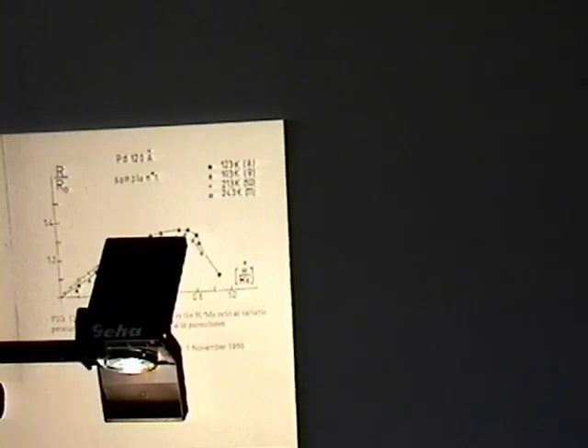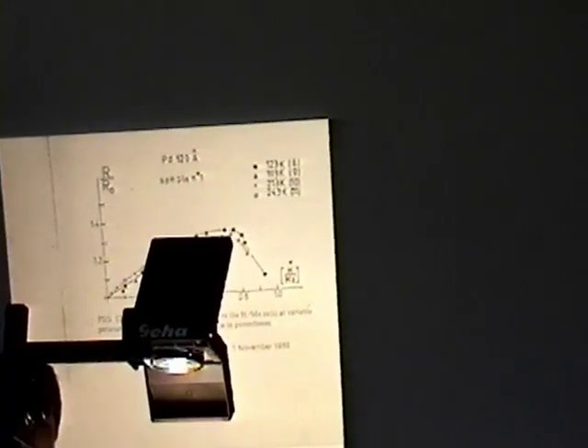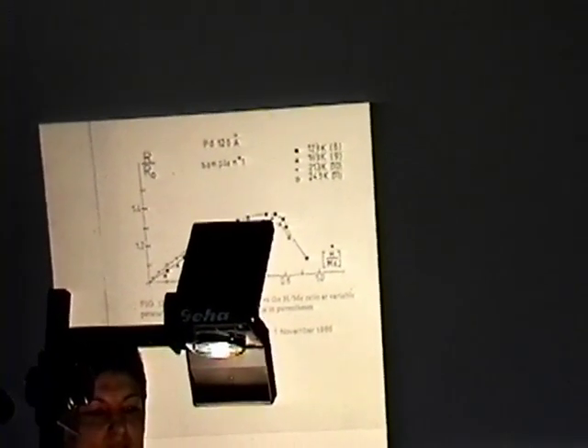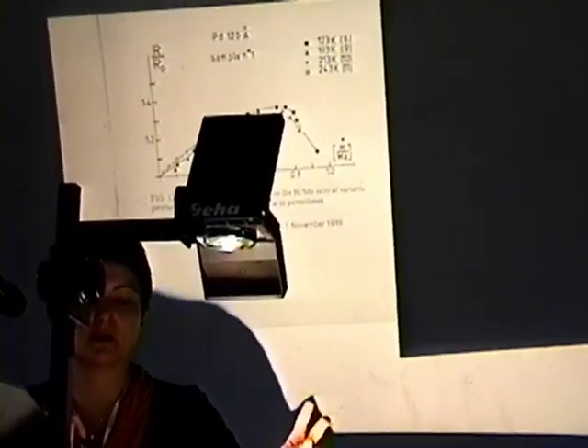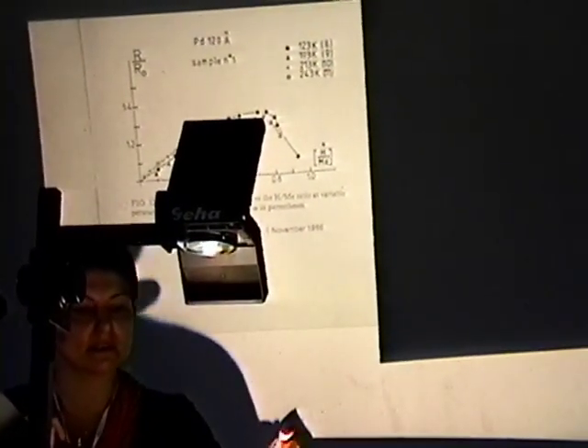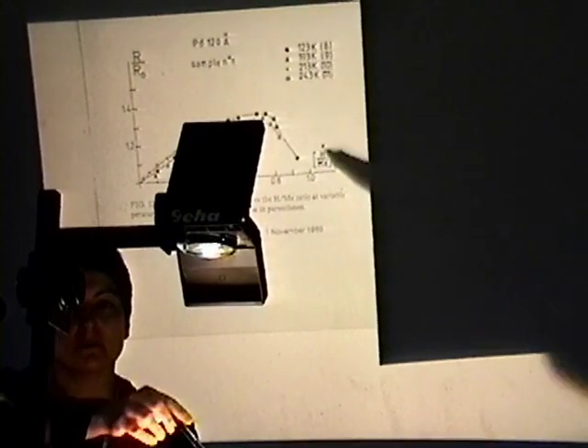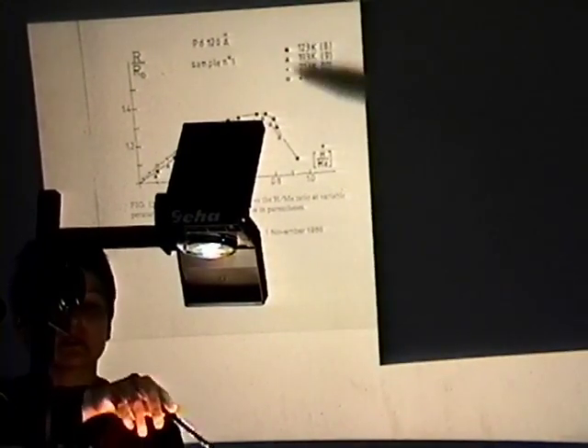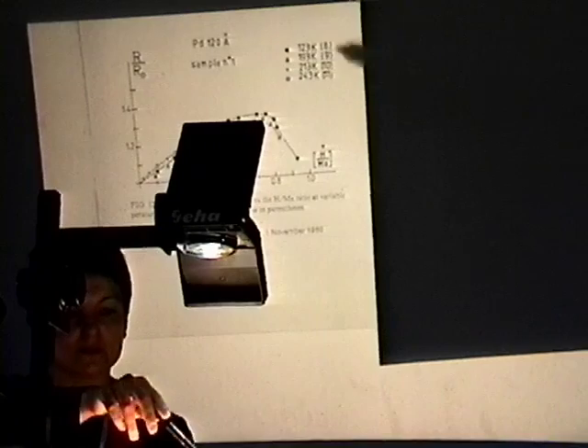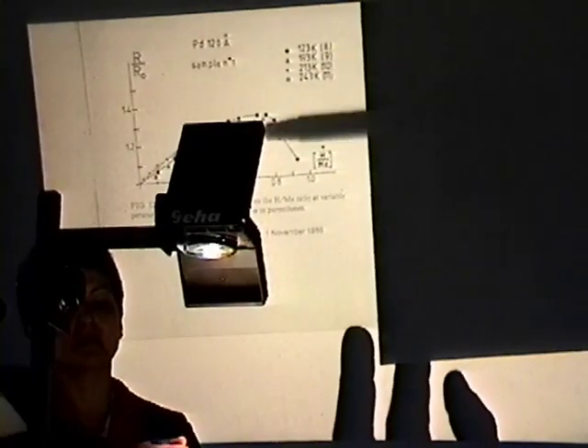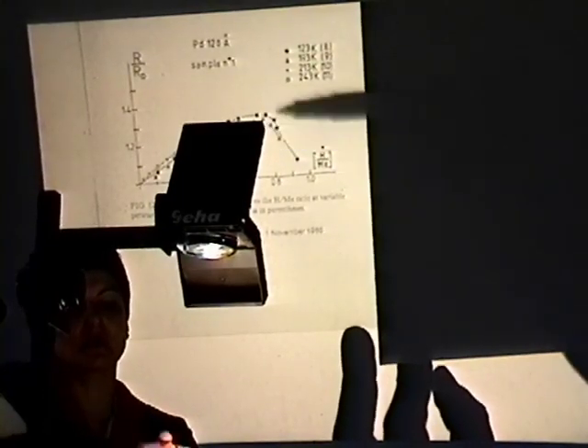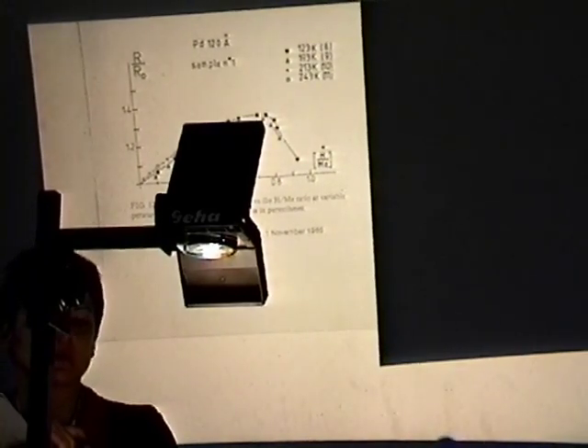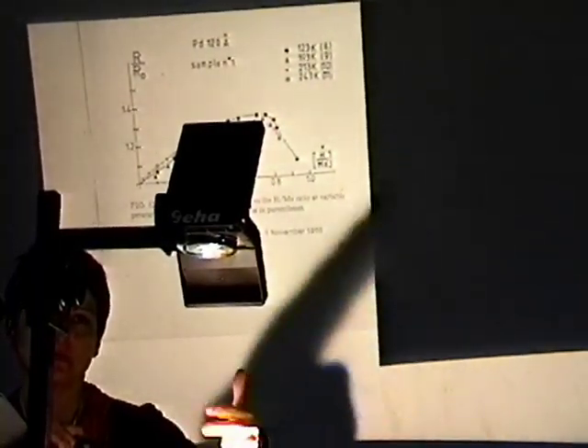This is another typical curve obtained in literature. Here you can see the relative increase of the resistance in thin films. In this case, a very, very thin film, this is a 120 angstrom film. The lower curve is the value at room temperature, and the others are at very, very low temperature.